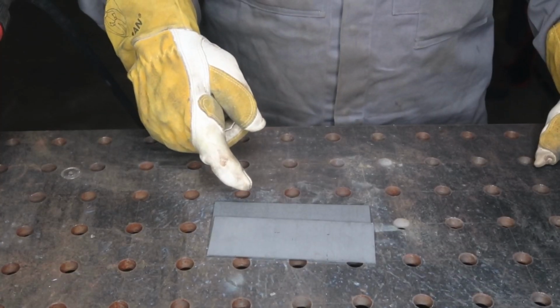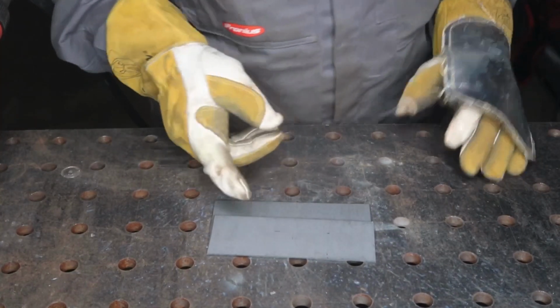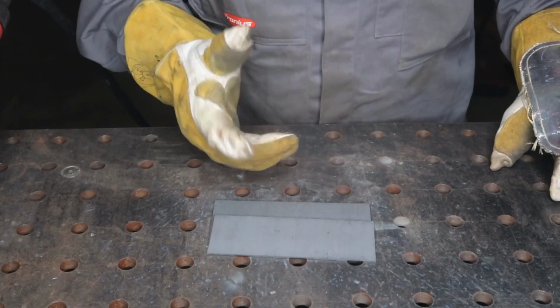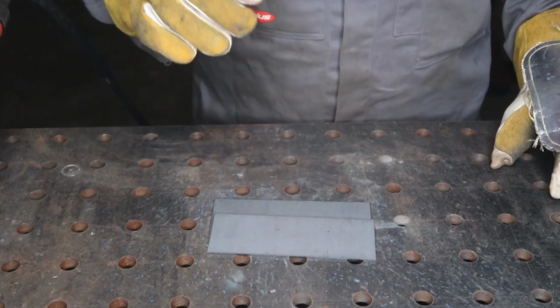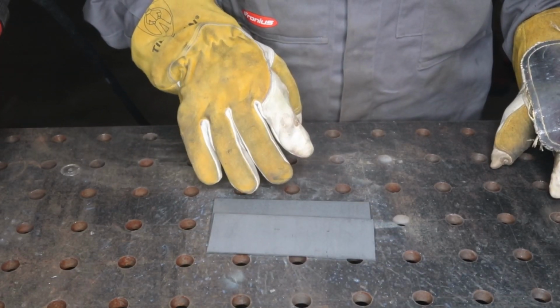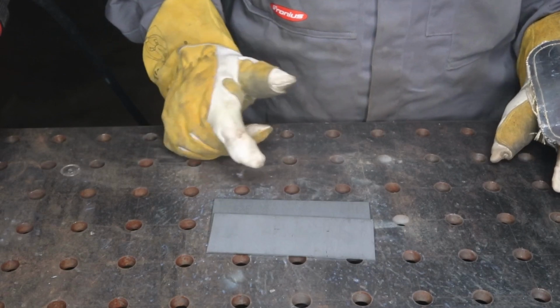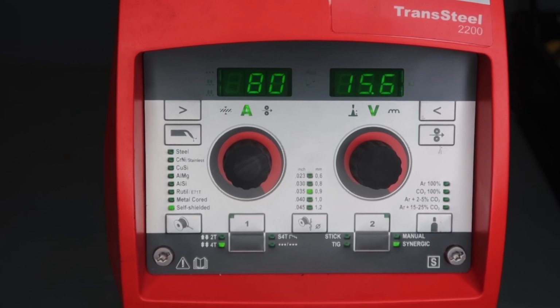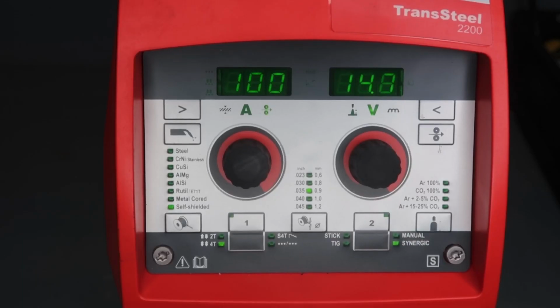We got some 80,000 material here. I got the machine set right at about 100 inches a minute at about 15.7 volts. We're gonna run this, see what our thickness limitations are, and I'll get it tacked up, see where we're sitting. We found it was best to run a 3/4 inch contact tip to work distance with a 15 degree drag angle for 80,000 plate with self-shielded flux core. Now, you don't want to exaggerate that work angle or specifically that contact tip to work distance. Towards the end of this weld joint, Corey starts increasing beyond 3/4 inch contact tip to work distance. And towards the end, it becomes really ropey, and you'll see it in the shot of the weld after he's done.